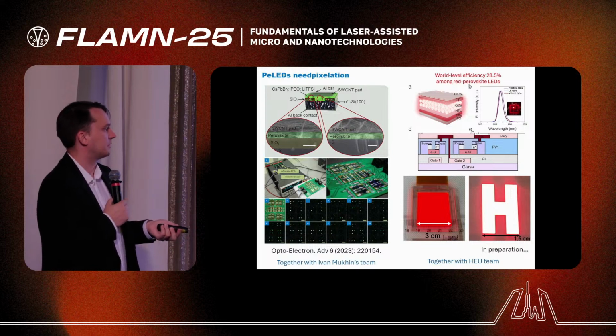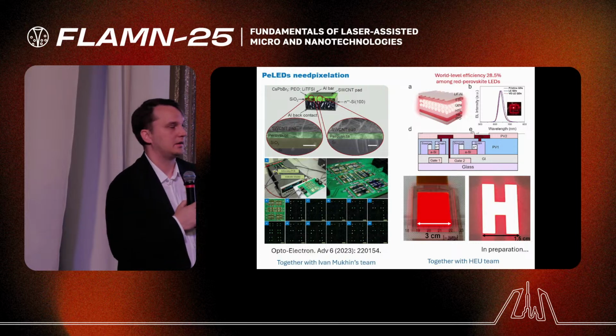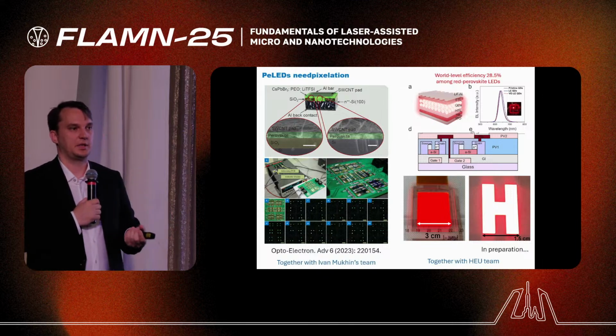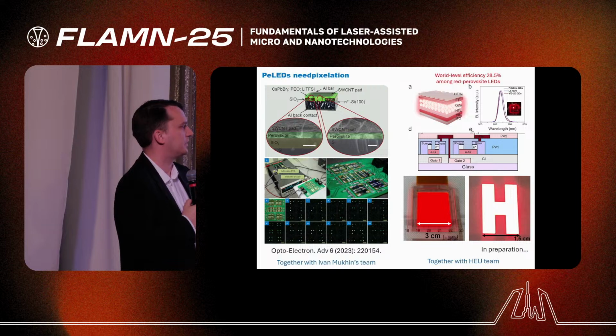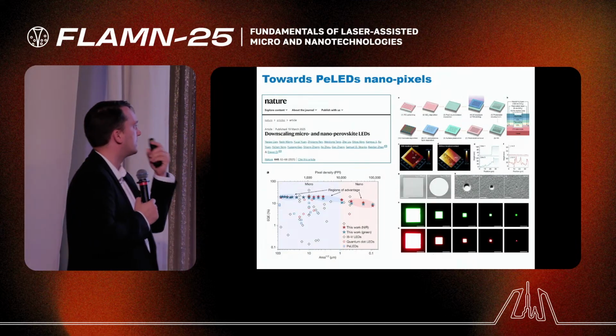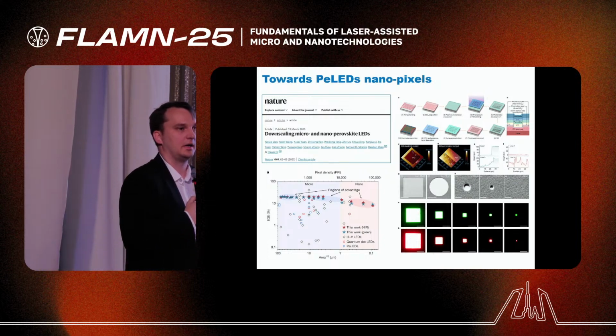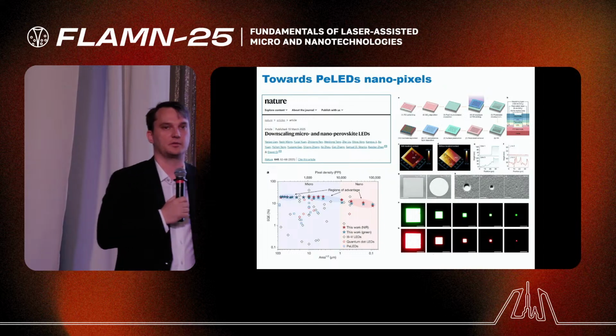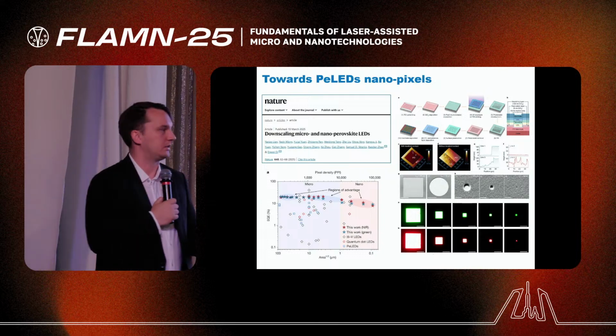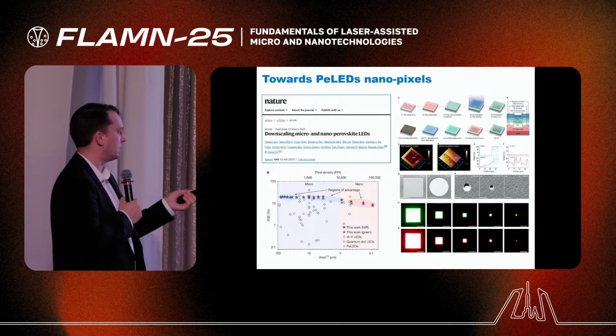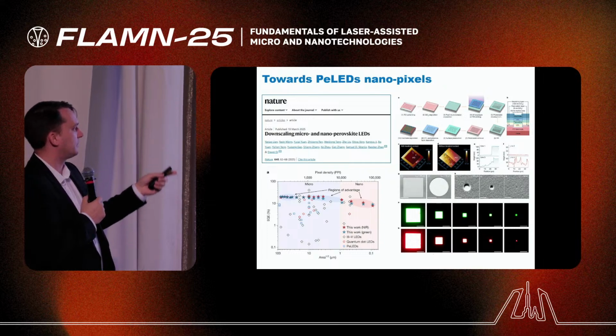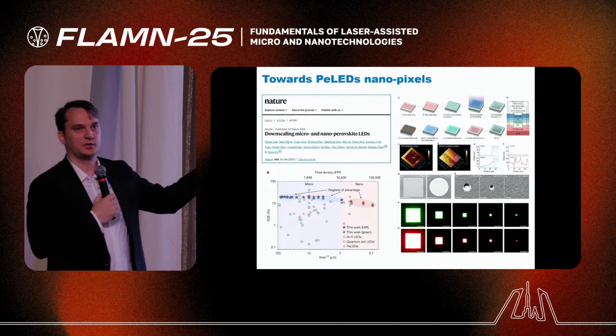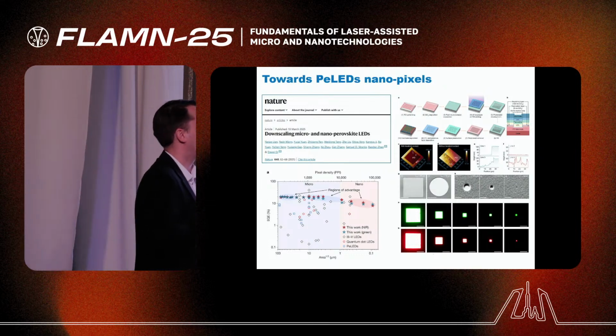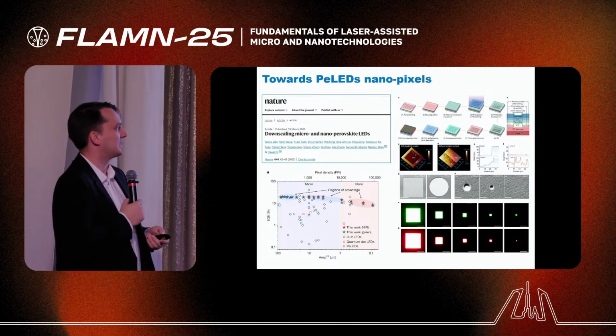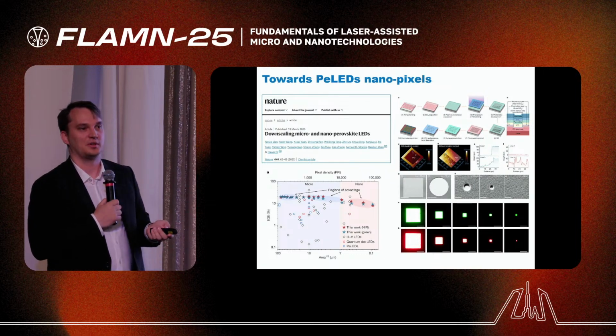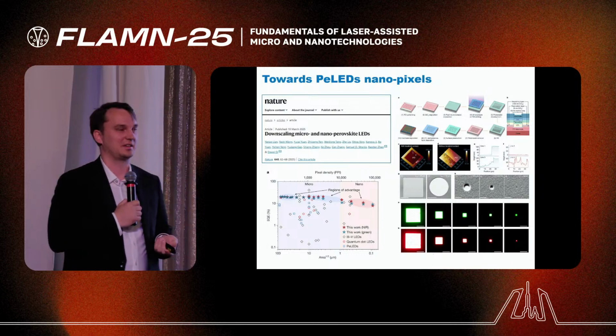But recently, in collaboration with our Chinese colleagues in our joint center in China, they use a TFT matrix with much smaller pixel size. The pixel size is around 10 micrometers, maybe 20 micrometers. But recently there was nice work from a university, from Professor Deva, and they showed that halide perovskites are very promising for nanopixelated LEDs. They compared different materials and showed that an area of less than 1 micrometer is good for halide perovskites. They used a lithography method. This is not laser ablated nanopixels yet. This is made by lithography. You see many stages were applied to create such nanopixels, and I think it's a good challenge for us to create such nanopixels by much cheaper technology like laser ablation.